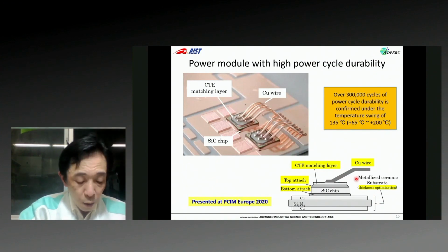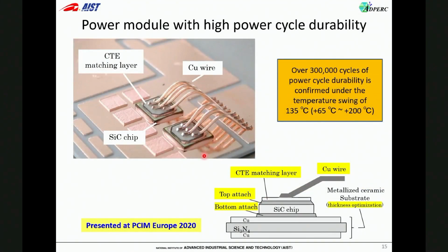The developed power module structure is shown here. By introducing the new design considering CTE difference, the power cycle durability is greatly improved. In this case, the power cycle durability of the conventional structure is only about 3,000 cycles. However, the durability of the improved design exceeds 300,000 cycles.